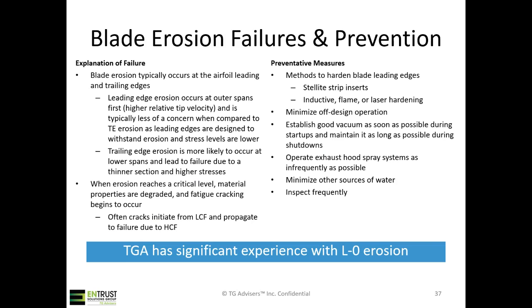I'd say the most important thing overall is that once your blade starts eroding, you don't want to take any measures to smooth it. You want to leave it alone. The erosion rates will actually slow over time. It's hard to judge erosion purely from photos, especially any sort of zoomed up photo, since the closer you are to the blade surface, the worse it's going to look. Really, it's more a function of how much mass the blade has lost.